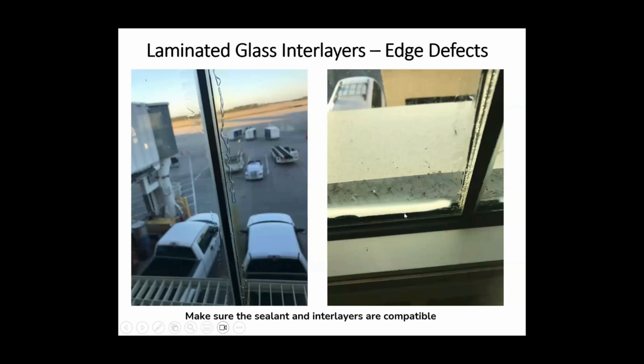And then the picture on the right, where you see white on the bottom of the framing system, when PVB gets really wet, it turns white. And so what you're seeing here is, my guess is for some reason this system isn't draining right, water stuck in there. Maybe the weep holes got sand in them or bugs.